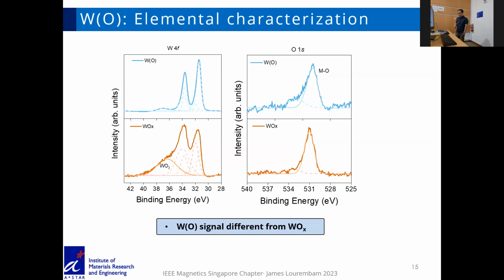So the main difference is at roughly 36 eV, which corresponds to the tungsten oxide signal. We see that it's mostly background in our multilayer. That means the amount of oxygen concentration in the system is very, very small. But of course, we know that there is oxygen in the system because we can see the oxygen spectra as well. That is in the right plot.